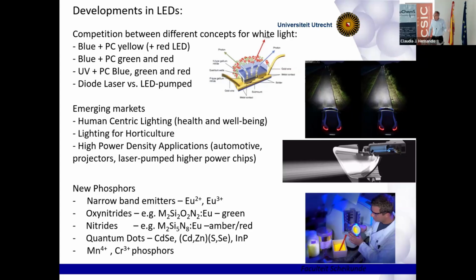You can have UV LEDs, the same material, indium gallium nitride, that is used for the blue LED. If you have a little bit less indium, more gallium, you can shift that LED to the near UV, and then you can have a UV LED with a blue, a green, and a red emitting phosphor. And also a big development is to replace the light emitting diode by a diode laser. Then you can get much brighter light sources. But for that, we also need new phosphors, new materials.